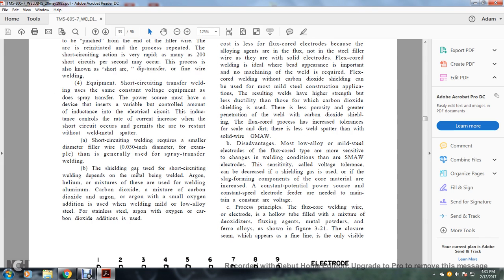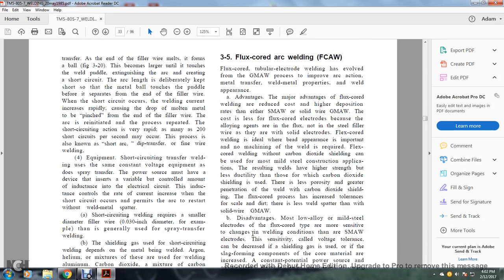The shielding gas used with short-circuiting welding depends on the metal being welded. Argon, helium, or a mixture of these is used in welding aluminum. Carbon dioxide, or a mixture of carbon dioxide and argon with a small oxygen addition, is used for welding mild and low alloy steels. For stainless steel, argon with oxygen and carbon dioxide additions is used.